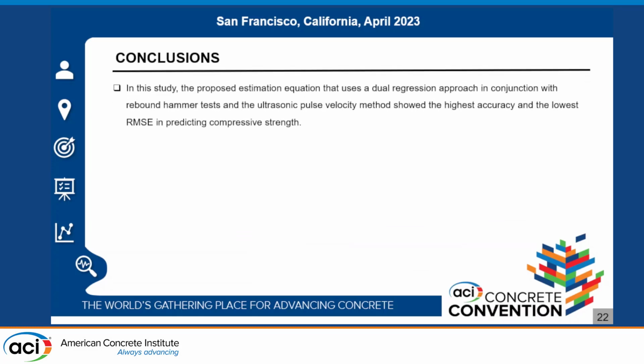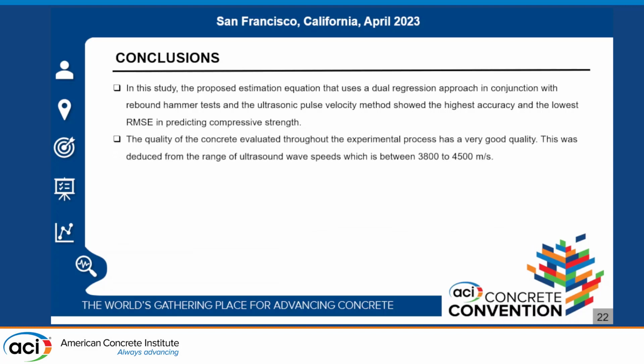Finally, we have reached the following conclusions about this research project. In this study, the proposed estimation equation that uses a dual regression approach in conjunction with the rebound hammer test and ultrasonic pulse velocity method shows the highest accuracy and the lowest RMSE in predicting compressive strength. The quality of the concrete evaluated through the experimental process is very good. This was deduced from the range of ultrasound wave speed, which is between 3,800 to 4,500 meters per second.